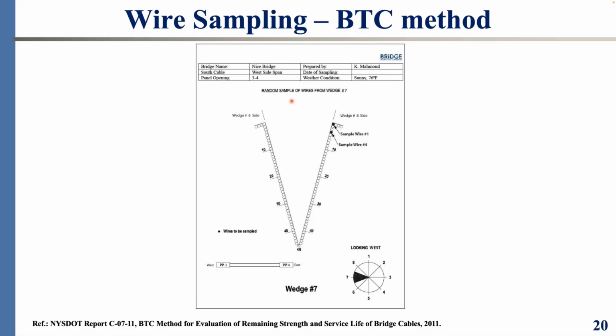or whatever random sampling process we are provided with in the BTC method, to basically avoid the visual bias or avoid the subjectivity of the inspectors. And the news is, when you look at these wires, good, bad, or ugly, they all, for the most part, don't look that happy with the stew of acid rain, de-icing salt and de-icing materials and debris and you name it. There is a stew of many, and you add to that the lead-based paint on the surface of the wire that, of course, seeps inside the cable cross-section. In other words, we try to eliminate all that, weed out this kind of bias, and do the random sampling.